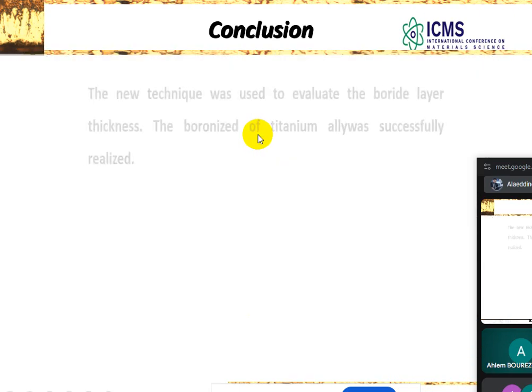So we observed the boron-treated surface after attacking for about 4 days in sulfuric acid. So this is the corrosion produced. There is no effect from the corrosion environment. And also, we have studied, it's a long study, so I try to summarize the electrochemical corrosion in sulfuric acid, NaOH, KOH, and HCl, the results that we have.